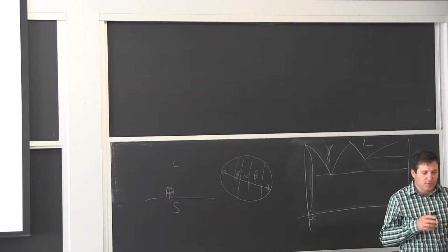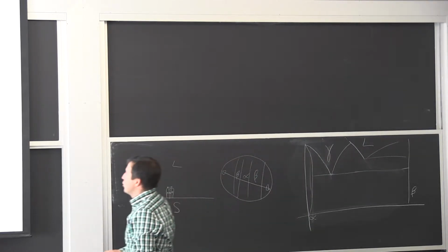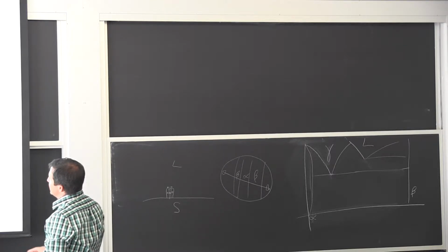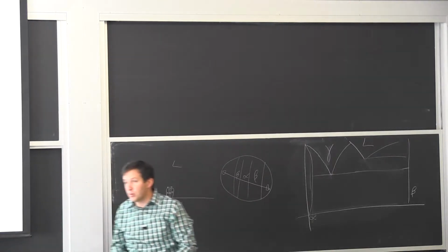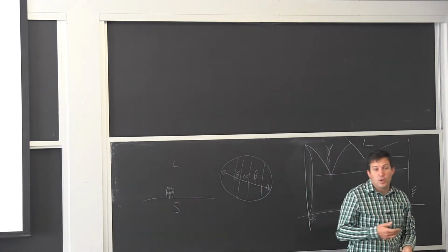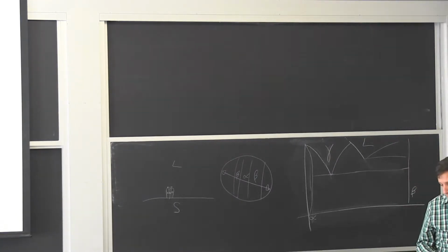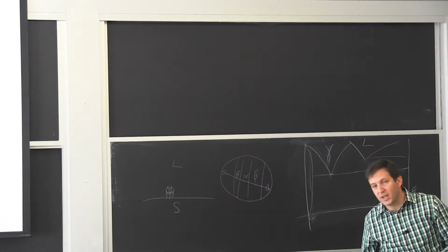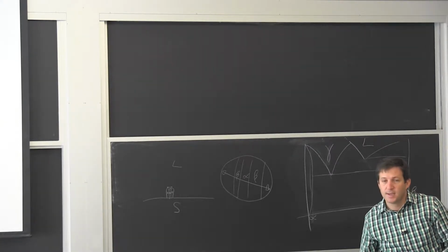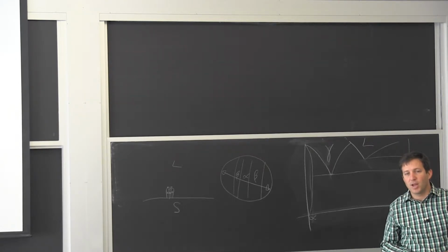So, if you think about a piece of steel that's being hot rolled, there were a lot of steps involved, one of which is how much you reduce each time, and what temperature you're going to process at. It's going to influence my grain size. If I'm not well lubricated, I get wear. I may have some surface defects. It's typical when you make threads. You need a lot of lubrication if you're going to forge threads. If you don't, you get reentrant corners, and these tend to favor a lot of crack initiation.